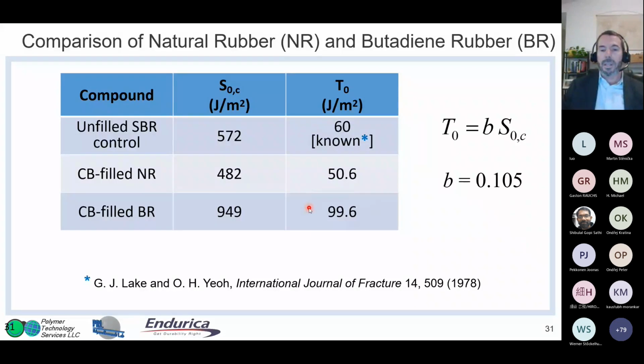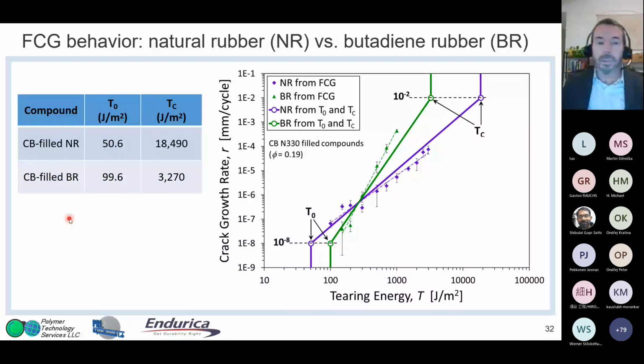And what you see is that the fatigue threshold for butadiene rubber is about double the fatigue threshold for natural rubber. But both of them are much smaller than the tear strengths for those materials. So you can see that here. Here are the tear strengths, 50 and 99.6. And sorry, the intrinsic strengths, the fatigue thresholds, 50.6 and 99.6. And then the tear strengths I showed you earlier are much higher, 18,500, 3,000. And what we learned was, if you assume some very fast crack growth rate for TC and some very slow crack growth rate for T0, 10 to the minus 2 for TC and 10 to the minus 8 for T0, you could actually plot those data points.